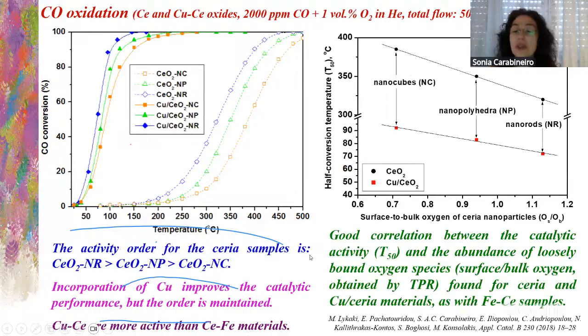And also we obtain a good correlation between the catalytic activity, the T50 temperature, and the amount of oxygen species here, both for the materials with and without copper, as we had obtained for the materials with iron.